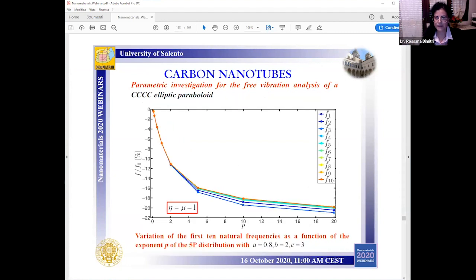So now, as a further parametric analysis, we account for the case of no agglomeration of carbon nanotubes within the matrix. This corresponds to the case where we assume eta equal to 1 and also mu equal to 1, as you can see here, for different values of P, I mean, for different values of the power-law index under some fixed constants, I mean A, B, C, that control the variation profile in each lamina. Here, we note that an increased power-law index gets a decreased relative frequency independently of the selected frequency.